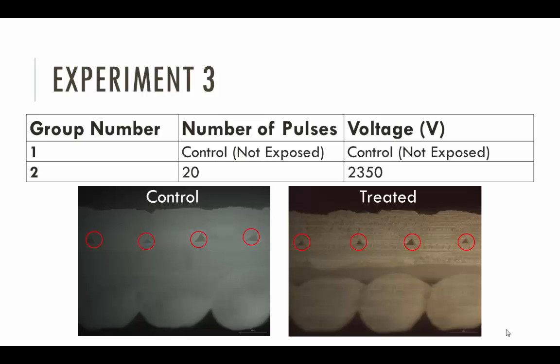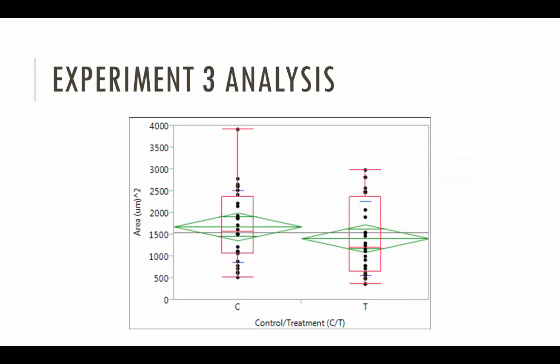After exposure, all samples were inspected under an optical microscope. 4 locations on each part were measured and recorded, and a sample size of 7 was used for this experiment. The data were then analyzed in JMP using a one-way ANOVA. The assumptions for ANOVA were checked prior to use, and no major violations were made to that assumption. The box plot reveals that the variation in both sample groups is very similar if we were to remove the outlier in the control sample.